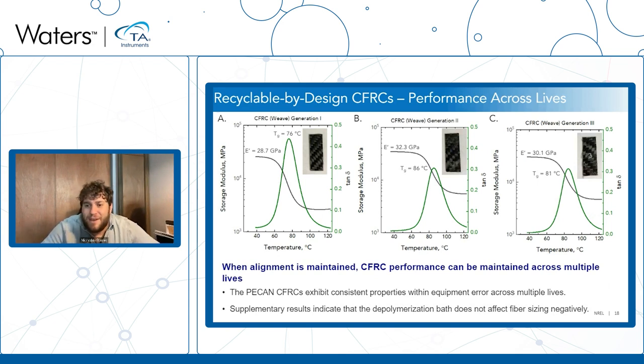Here you see DMA, which is definitely the major workhorse of our lab itself. And you see that on the first life of these materials, we have materials with great storage modulus, wonderful plateau modulus, and moderate glass transition temperatures around 76 C. We can then take our fiber, reinfuse it with virgin resin, and on the second life of our material, we can still get excellent performance. In fact, we actually see some increases to the glass transition temperature of the material and the storage modulus.